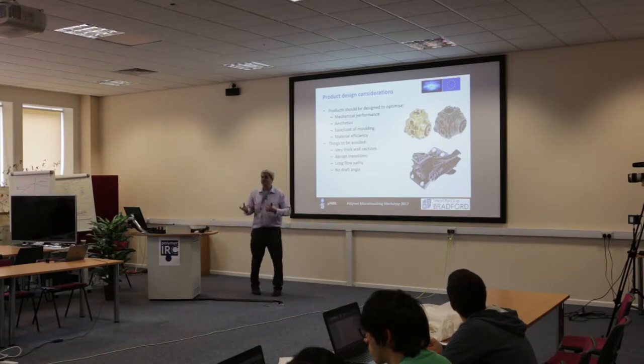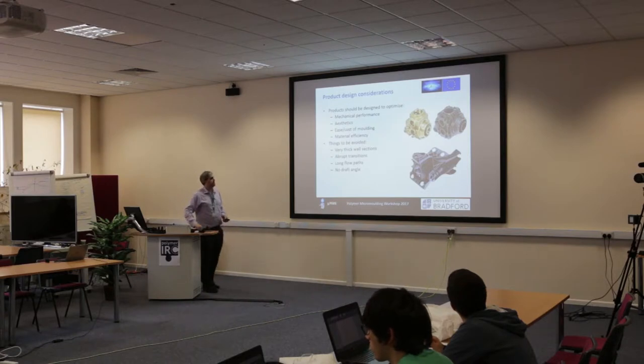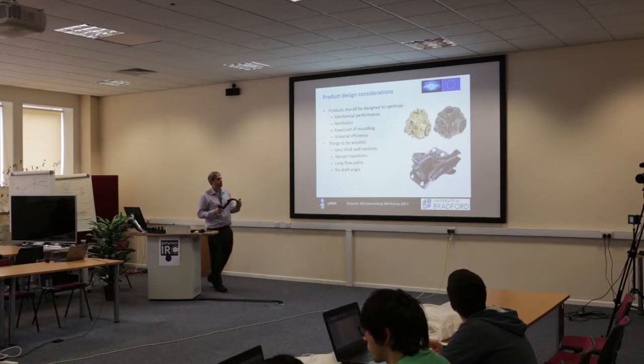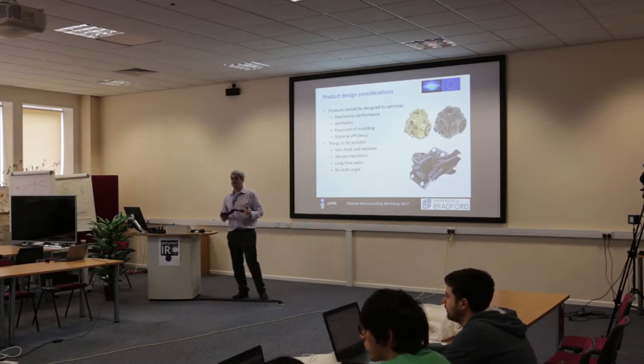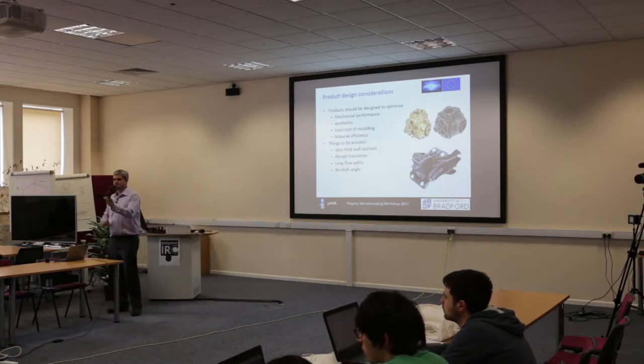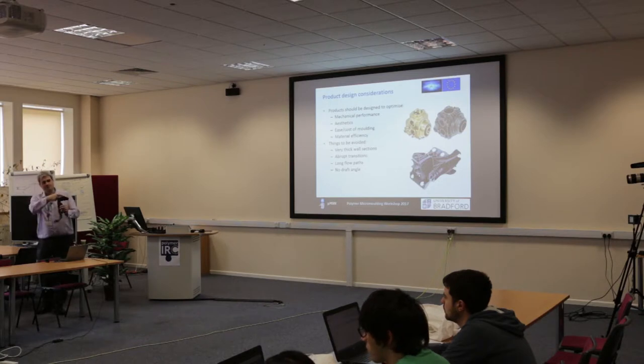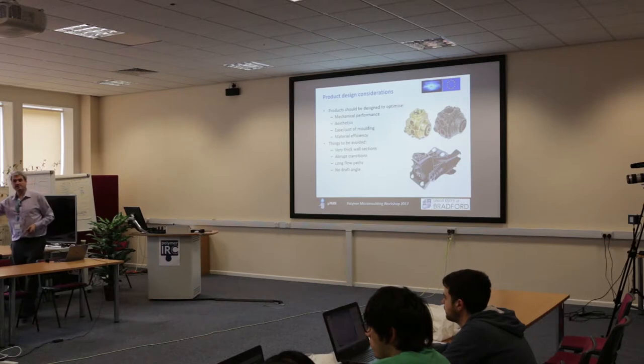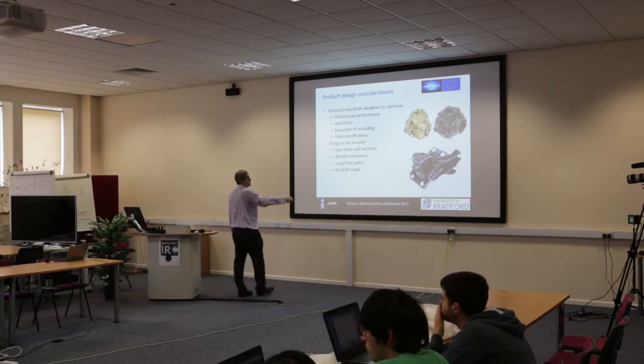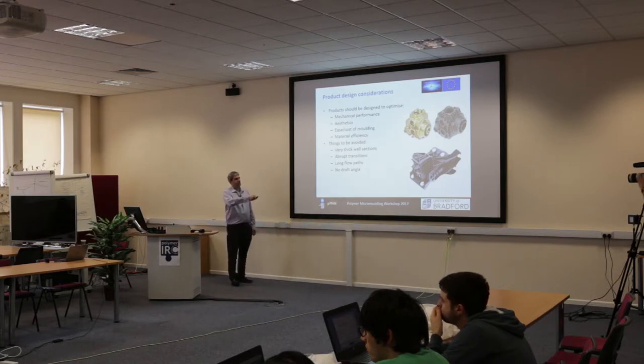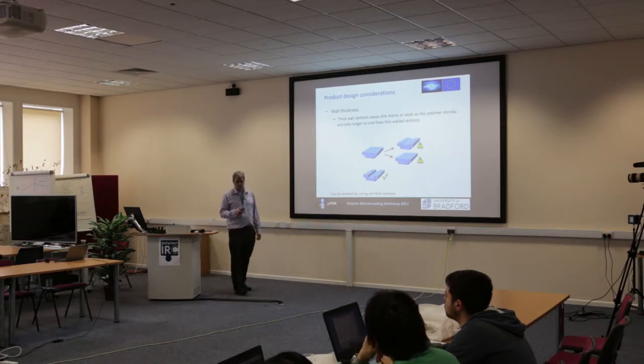Shrinkage is an issue we want to minimize. Most injection-molded parts tend to have fairly thin-walled, rib-like structures to give mechanical strength while avoiding thick sections, because thick sections are difficult to pack during the hold phase. Thick sections cause a reservoir of melt in the central section; if that region can't be packed because surrounding areas freeze first, the material is drawn inward by shrinkage, producing a sink mark defect — very common on injection-molded parts. Even worse, internal voids can also occur if the material adheres to the mold surface.